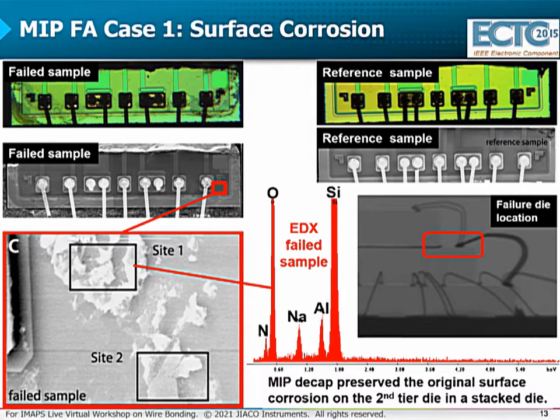Now let's mention how the samples were prepared. Let's start with this failed sample on the left. First, the package was partially decapsulated, and saline contamination was deliberately introduced on the second die in the stack. The package was then refilled, and the refilled devices were exposed to ultra HAST testing. After that, a leakage was verified. The reference sample on the right has undergone the same preparation procedure, but there was no deliberately introduced contamination.